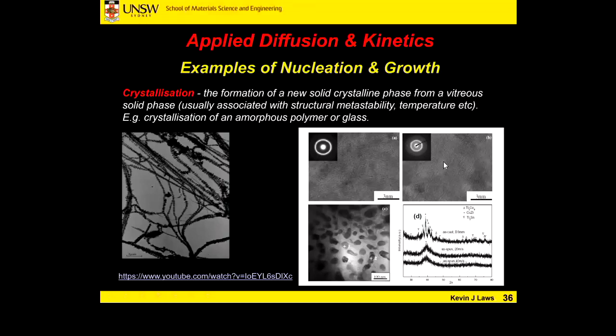Okay, so one of my fields of research is metallic glasses, amorphous metals. We cool them quickly, they don't have time to crystallize. But if we heat them up slowly to beyond their glass transition temperature, okay, so plastics, thermoplastics, metallic glasses, ceramic glasses all have a glass transition temperature. If you heat above that glass transition temperature for a long enough period of time, that material will also crystallise. This crystallisation is going to be probably homogeneous. It's happening very, very slowly in a very viscous supercooled liquid. All right, so we can see here homogeneous nucleation and growth of crystals in a vitreous metal.